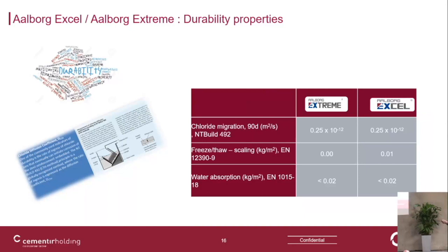So with these mixes, of course, we try to have a very dense material, and for the durability, it's also a material that has a low porosity. So also for chloride migration, the values are very low. And we did also the tests for the freeze-thaw cycles, and we see that there is almost no risk for freeze-thaw. These values are very low, almost zero. And also the water absorption is very low.